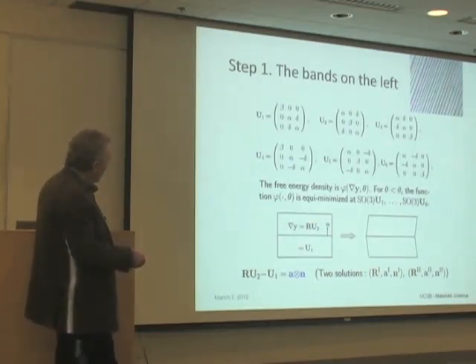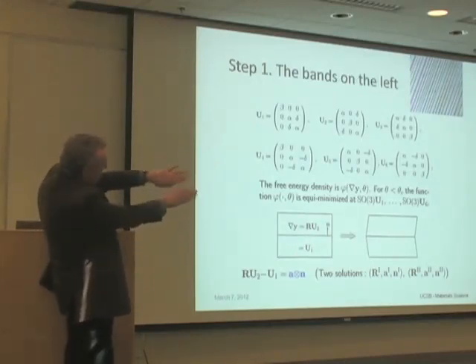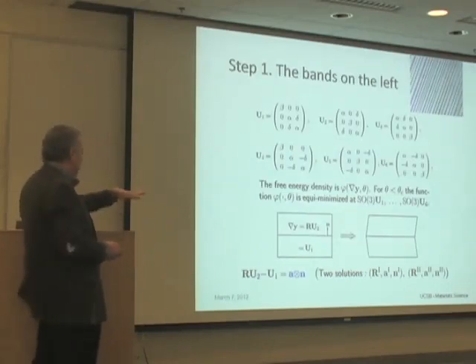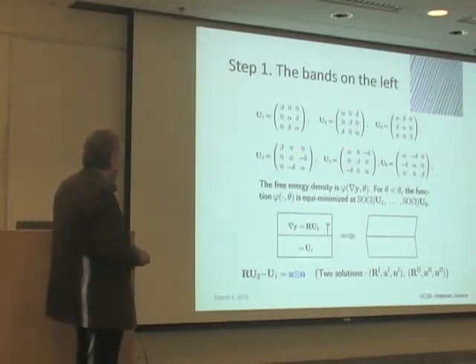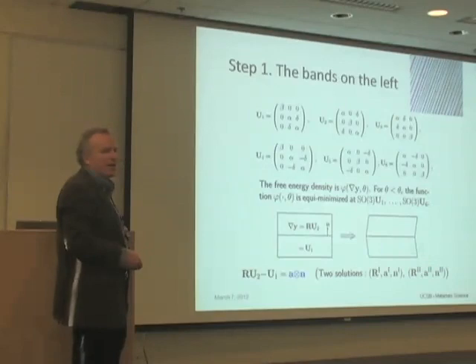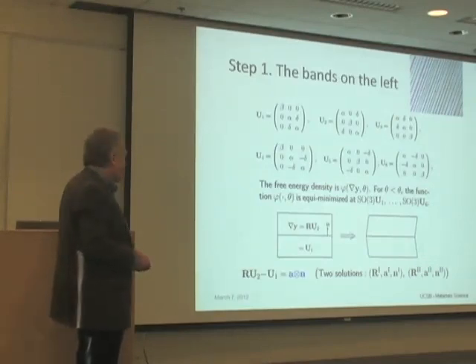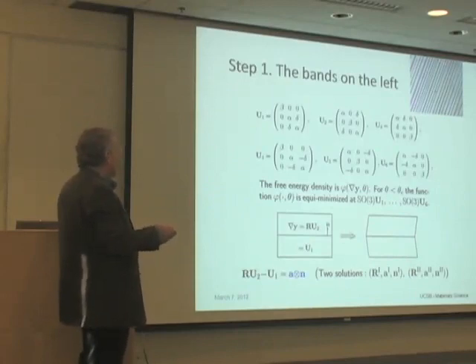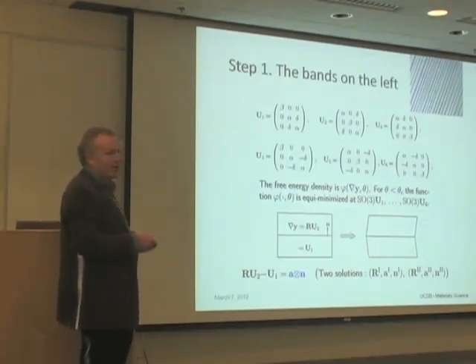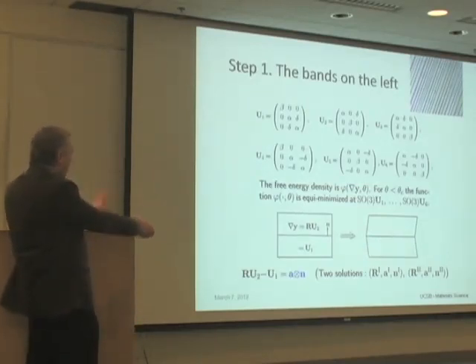So that compatibility condition means that these two matrices differ by a rank 1 matrix. Again, the details are not important, but there's a compatibility condition across that interface, which means that the deformed shape doesn't come apart and sticks together. It's a continuous deformation. And that's an algebraic condition. If you solve that condition, you get two solutions. You interpret them as type 1 and type 2 twins. All the geometry of that picture agrees with that picture. The normal is predicted correctly. If you go to atomic scale, the shape changes are correctly predicted. Everything in that calculation agrees with this. For one of those types, in fact, it's the type 2 twin in that case.